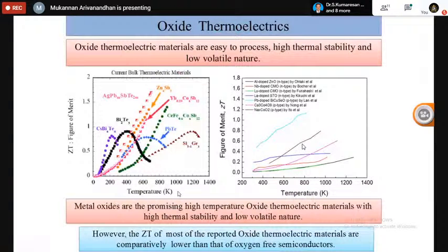And that is the reason people have moved towards oxide thermoelectric materials. Here you can see the comparison. This is the oxygen-free thermoelectric material. Most of them are semiconductor-based thermoelectric materials, and as I said before, only silicon germanium can withstand more than 1000 Kelvin, right? Whereas here you can see the oxide materials. Most of the oxide materials are quite active even after 1000 Kelvin, and the performance can be enhanced by properly engineering the material.